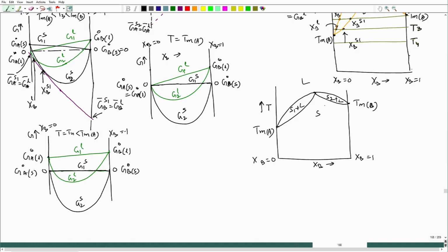So now the only difference between combination 2 and 3 is that in case 2 the two G curves were going downwards, and in case of combination 3 the G curves are coming upward. So why? Because in this third case, combination 3, the solid enthalpy of mixing is highly negative. So solid is stable. That means solid would be stable beyond the melting points of both the metals.